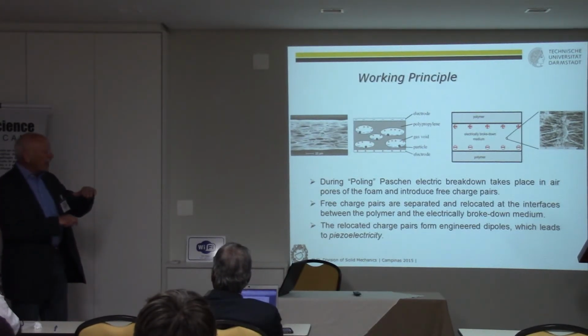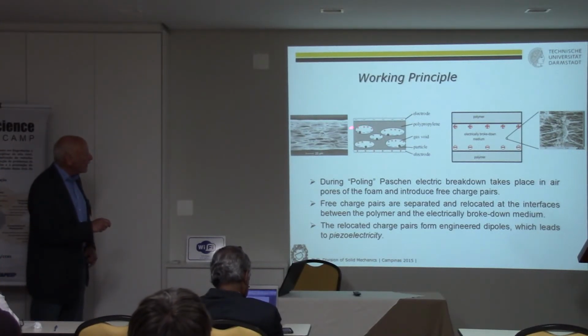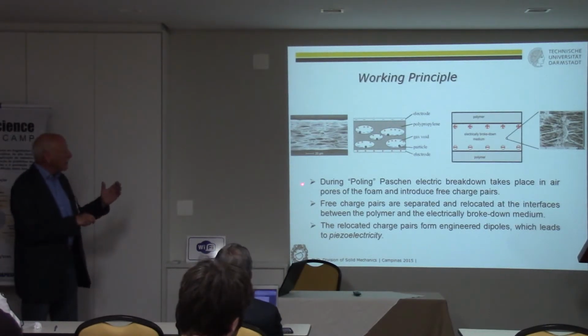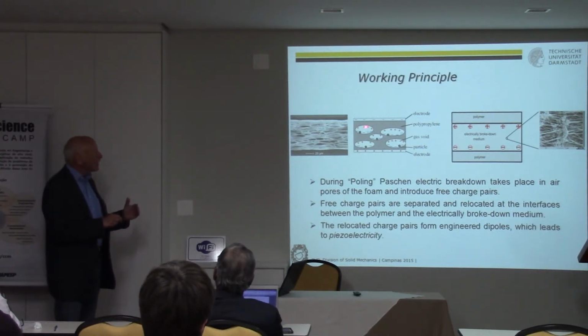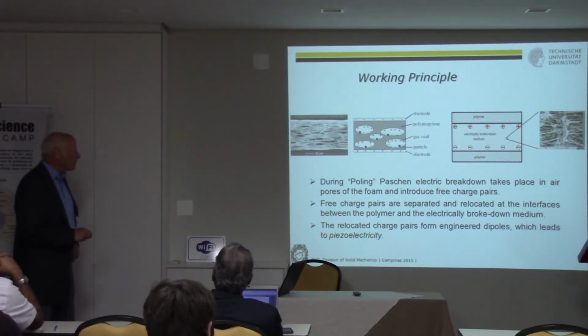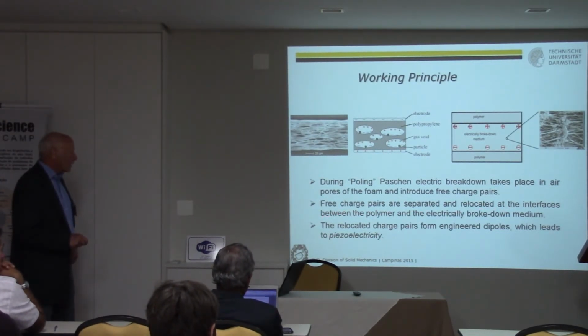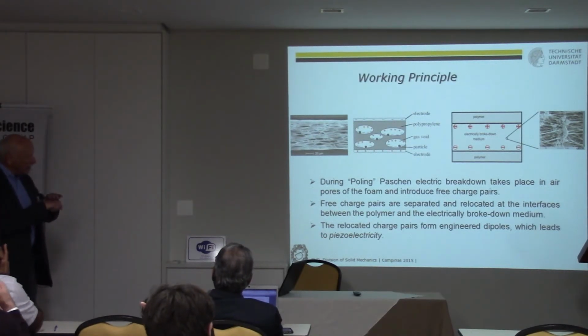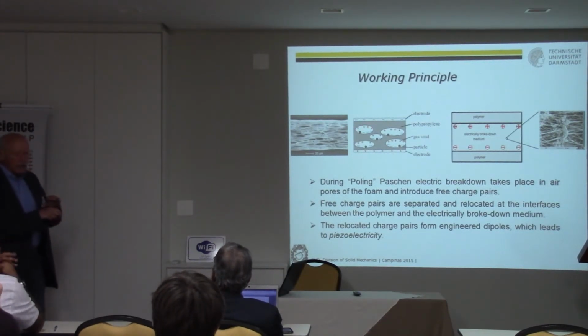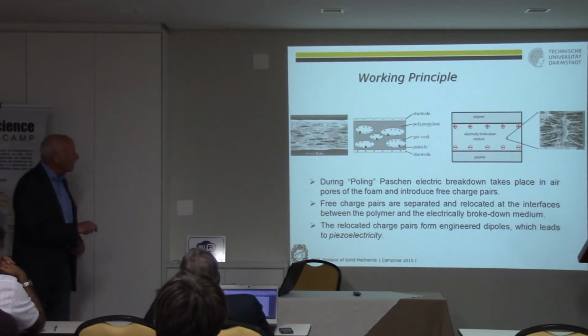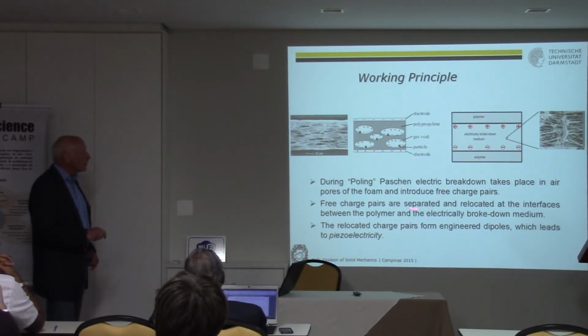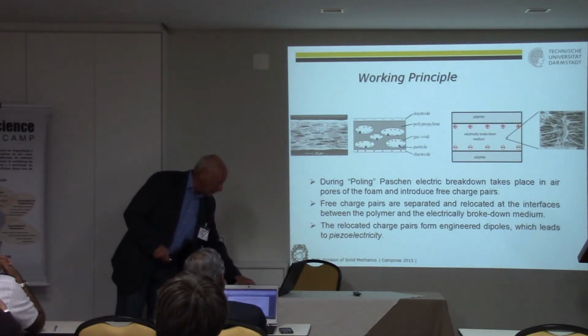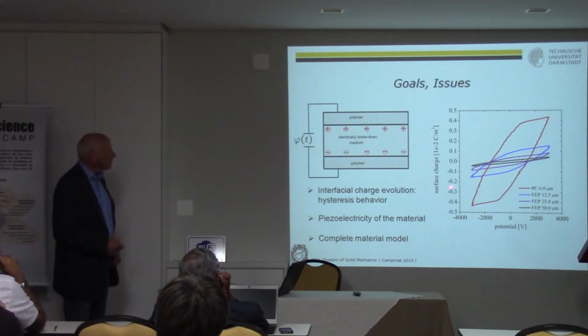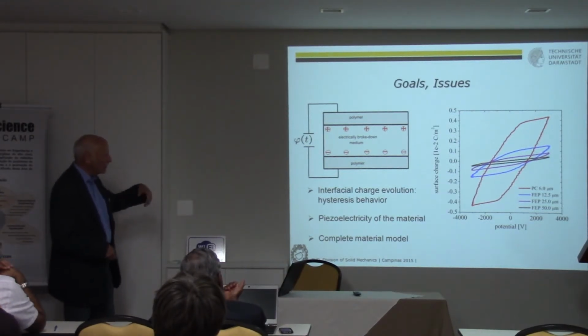Yeah, and on account of the acting field, the charges are separated and transported to, say, the interface between, say, the gas and the, let's say, solid material. And then at these interfaces the charges are really fixed. Yeah, they are trapped. Yeah, and these charges of course form then engineered dipoles. Yeah, and this leads to piezoelectricity. This is a very nice procedure, and what you see here, for instance, if you apply this electric potential in say two directions, up and down,